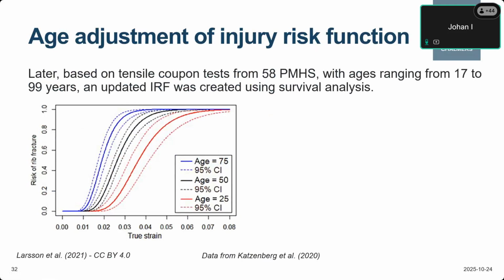And here we can see that we have an age effect. The blue curve represents 75 years old, and we can see that the onset of fracture is then less than 1%. The black one is for 50 years old, and the red one is for 25-year-old, and then we can see that the onset is moved up to 2%.